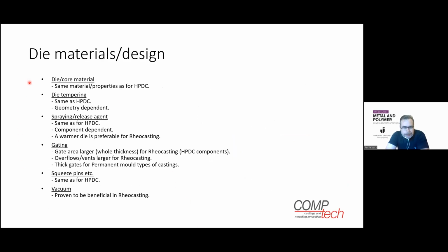The tools, or the dies: we use the same type of steel in the Rheocasting tool as we do in high pressure die casting. We have the same heat treatment of the steel and so on, so there's no difference here. Die tempering is perhaps more important from a part geometry and die lubrication standpoint, rather than the switch from high pressure die casting to Rheocasting. In general, if we are able to cast at a higher die temperature, it's beneficial for the process, but that's mainly decided by the geometry of the part.